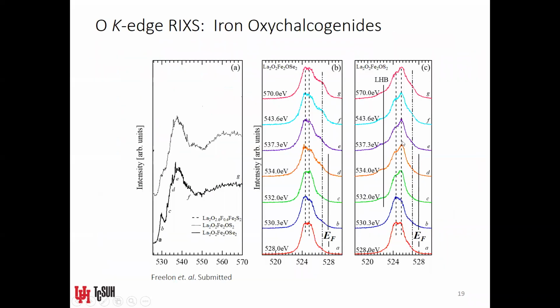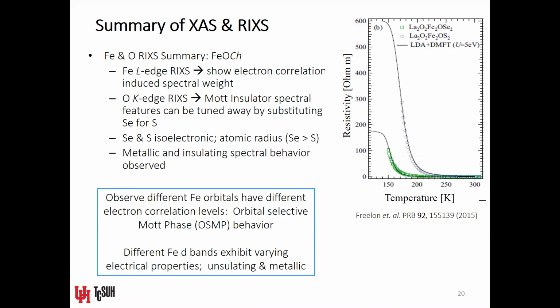Let me go back. So here at the oxygen edge RIXS, this is RIXS, so this is occupied density of states. You'll notice that you have these high energy features in the sulfur compound here. These are Hubbard band features, but they don't exist in the selenium compound. And that lets you know that the sulfur compound is actually more of an insulating material than the selenium-containing compound. So we can actually tune the Mott insulating behavior as we substitute from selenium to sulfur.